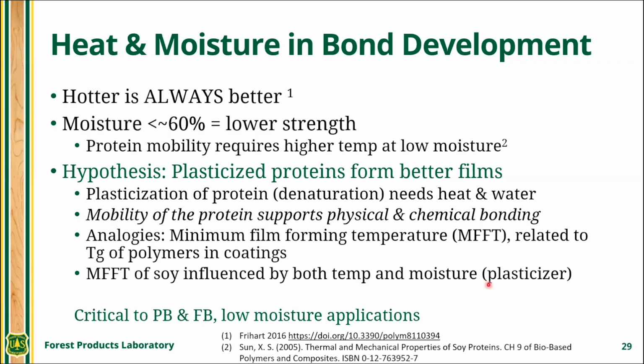And re-emphasizing temperature and moisture, or whatever plasticizer you have. Could be glycerin, could be urea, could be whatever. This point about moisture enhancing or facilitating the bond formation, the protein-to-protein interaction during bond formation, is really critical to fiberboard and particle board applications where you are required to have very low moisture. The process just doesn't allow the moisture. And therefore, I think this is one reason why particle board and fiberboard have seen less success in protein adhesives, especially plant-based protein adhesives, than plywood has.